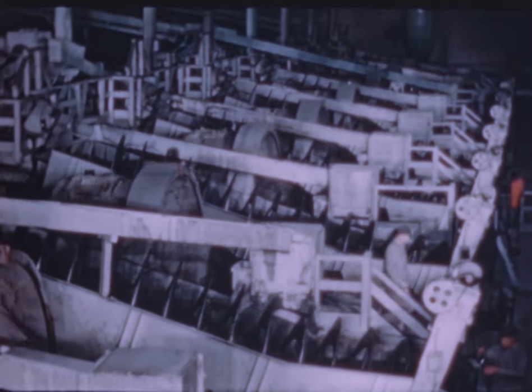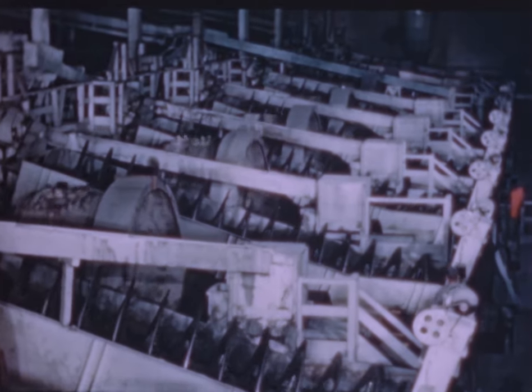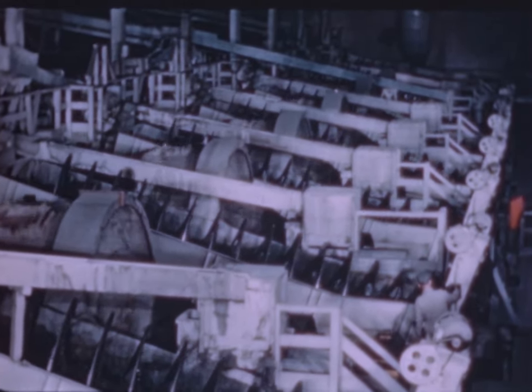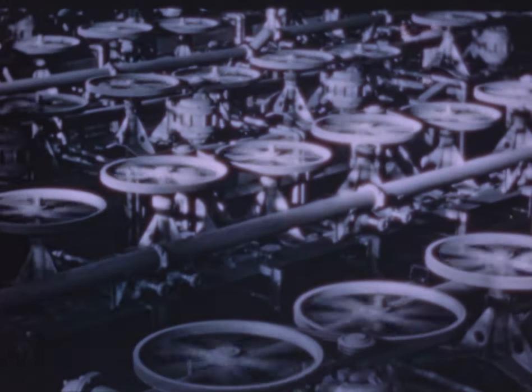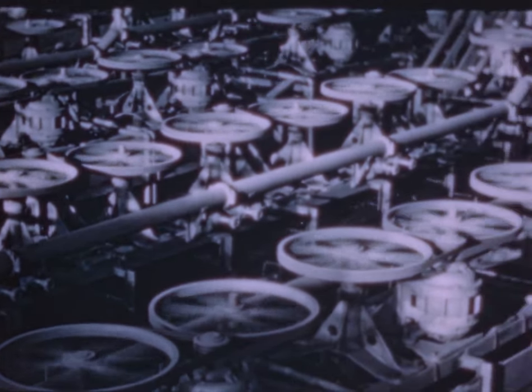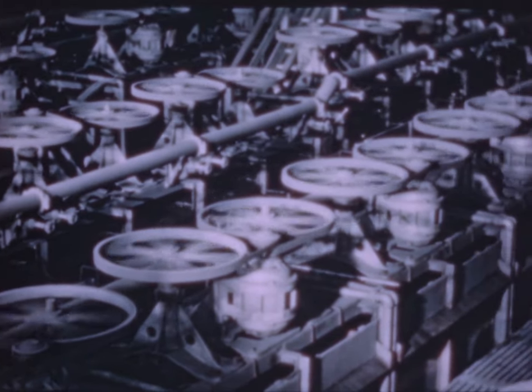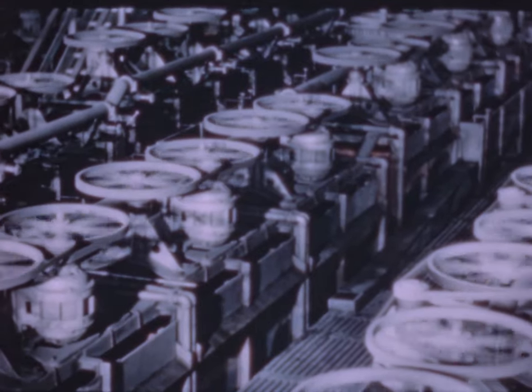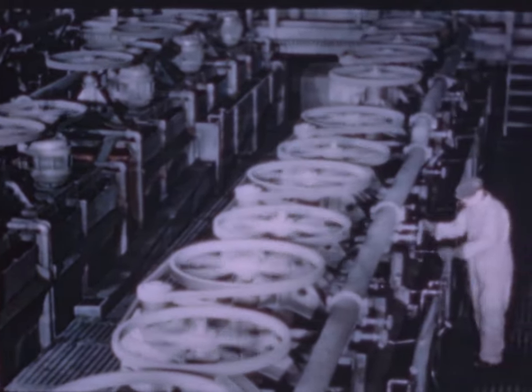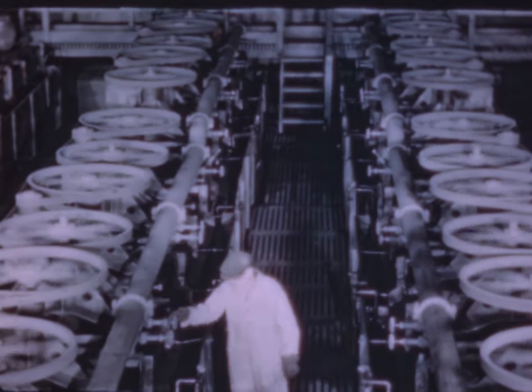With cast iron balls and water added, the revolving mills grind up the ore to the size of fine sand, then discharge it into the classifier, where the coarser particles are returned to the mill by a screw conveyor. No ore can escape this circuit until it is ground fine enough to free the valuable mineral particles from the worthless rock, so that they can be separated by flotation. In the flotation process, the finely ground ore, mixed with water and certain oils and organic compounds, is aerated, forming a froth. The sulfide mineral particles cling to the surface, while the worthless rock sinks to the bottom of the cells.